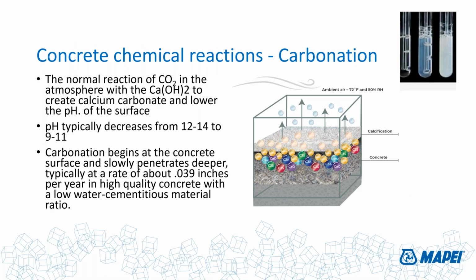If you allow the concrete its normal time to cure, what's going to happen to the calcium hydroxides that are on the surface of the concrete slab? Over time, they're going to react with the carbon dioxide in the air, and they're going to carbonate. And as that calcium hydroxide reacts with the CO2 in the air, it becomes calcium carbonate. So that's kind of why a concrete slab will change color a little bit over time, from a greenish looking material to a little bit paler, whiter thing, because calcium carbonate is white.